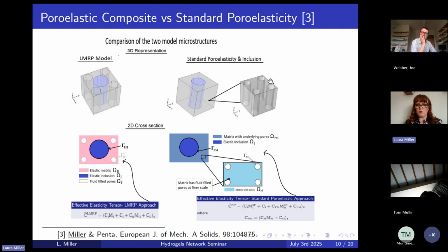And if, when we did our simulations, we found that we were getting vastly different results between these two setups, we could be confident that it was worthwhile to have developed such a model, because if the tissue is showing the three phases at the same scale, you should be able to account for them all at the one scale, rather than doing this two-step process to try to best approximate what you're actually seeing. And spoiler alert, the model was worthwhile developing. So that was very good news.